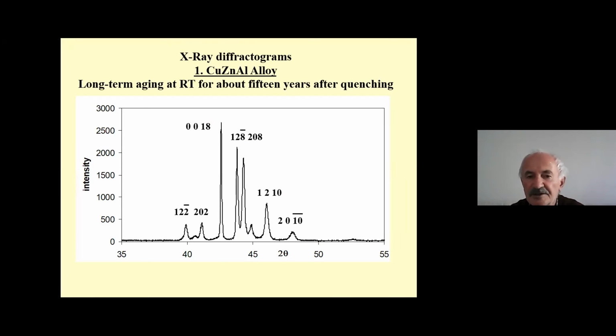This is an X-ray diffractogram taken from the copper-zinc-aluminum alloy sample after quenching, following long-term aging at room temperature for 15 years after quenching. As you can see, peak intensities are different, and this profile exhibits superlattice reflections. Also, in this diffractogram, these peak planes are important. These are 1 2 2, 2 0 2, 1 2 8, 2 0 8, 1 2 10, 2 0 10, and others.